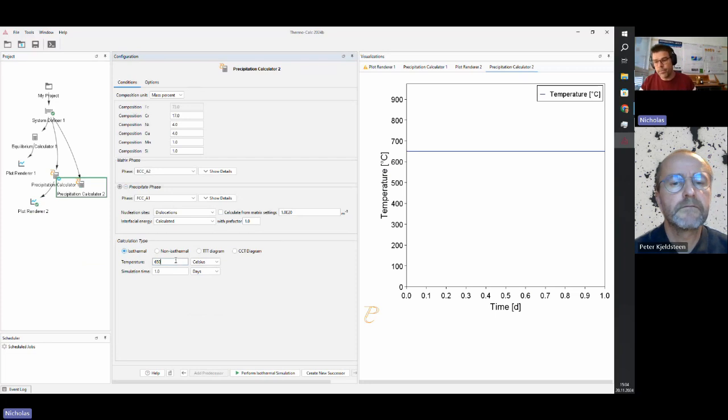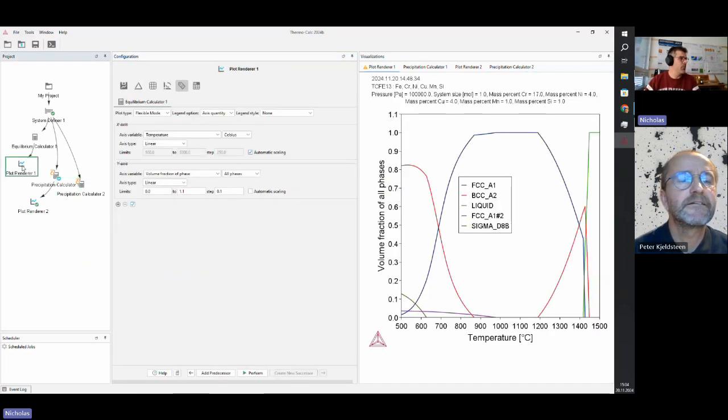And again, I've never tried this. I just hope it works, right? The point about the higher temperature is, if you go back to the equilibrium calculation, at higher temperature the fraction of precipitates could be lower. So the driving force for the formation of the precipitates could be lower, but the mobility is certainly faster. It's a lot higher, yeah. So the question is, who wins, a bit, right?